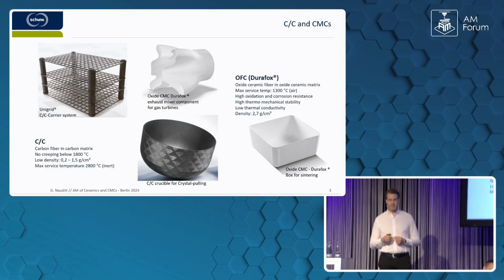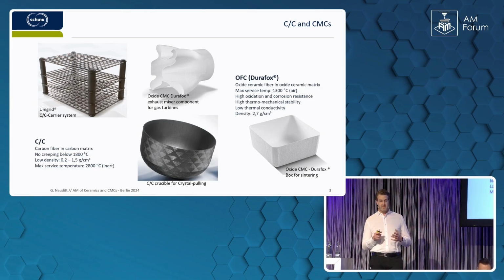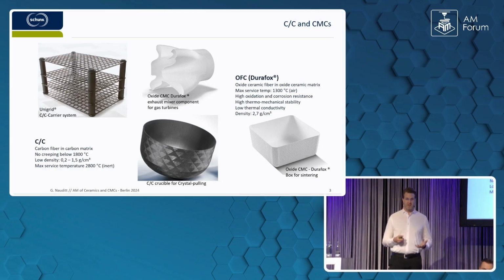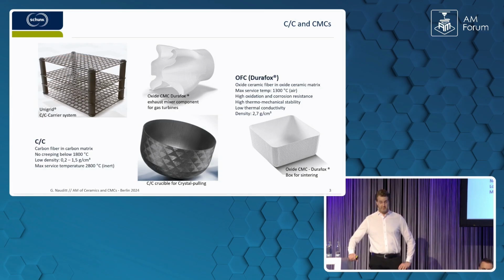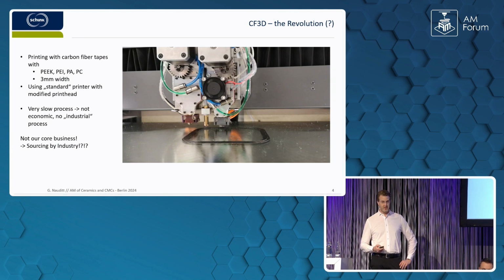The carbon-carbon, for example, you can heat up to 3000 degrees C as long as there is no air present. And it has a very low density. And there is no creepage, like, for example, with many metals, they begin to creep. Carbon-carbon will not, even at temperatures of 1800 degrees C. And of course, we are also printing a lot.